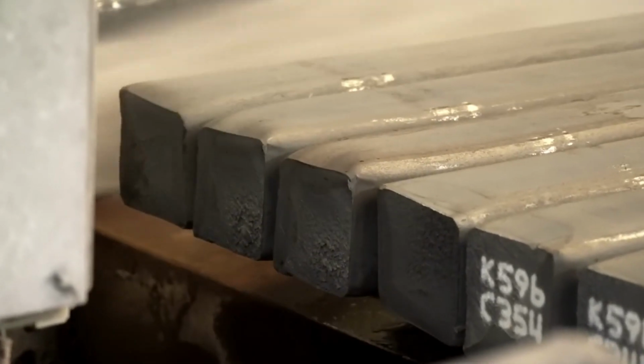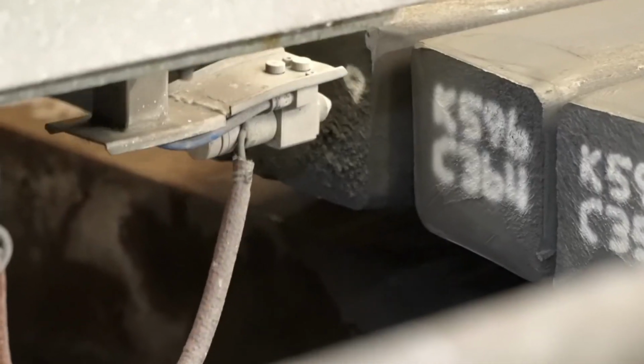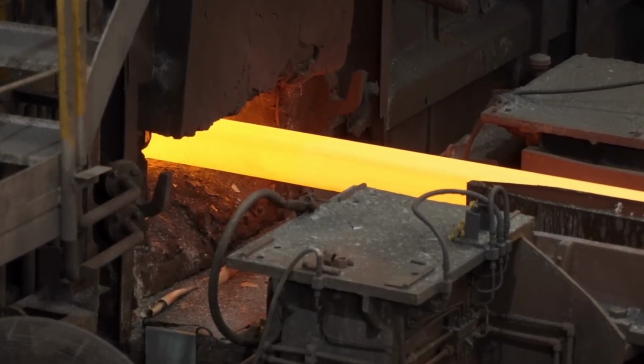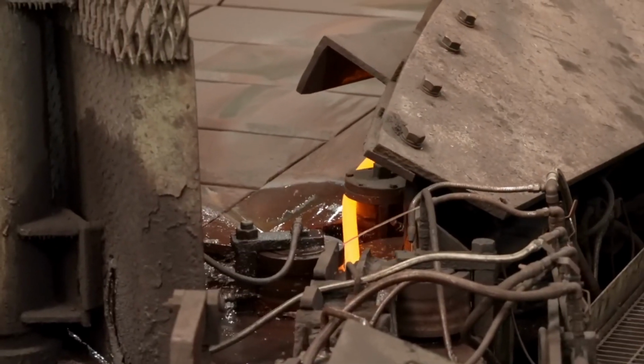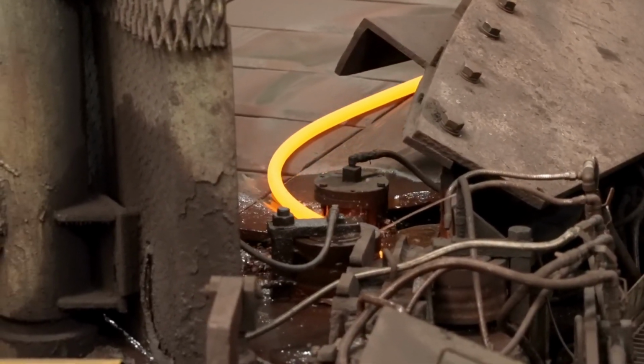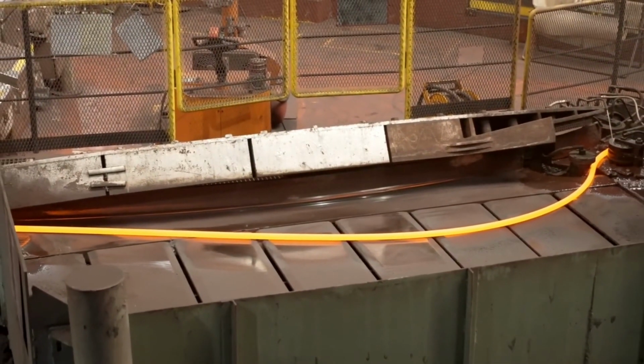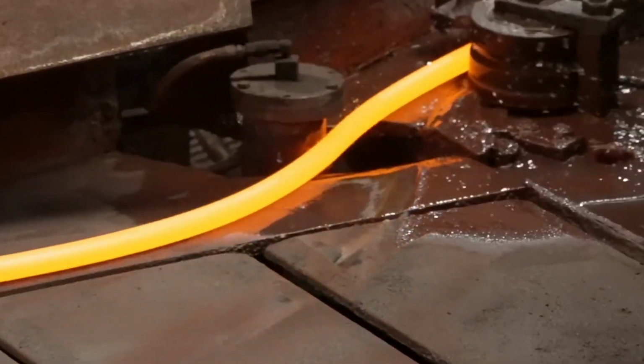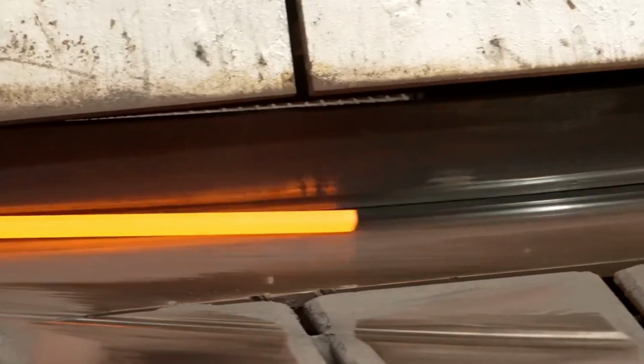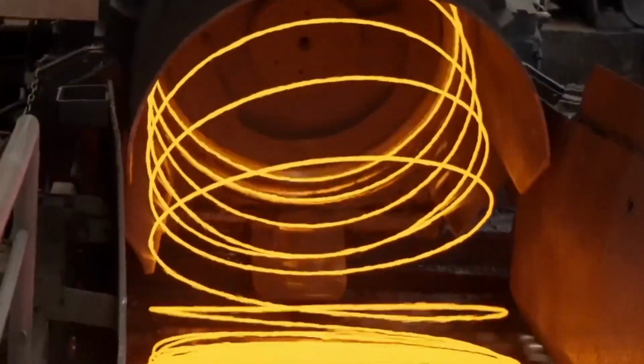Dozens of thermocouples monitor heat across the surface. If a cold spot appears, burners ramp automatically. If one region overheats, fuel drops instantly. Uneven heat creates soft spots and tears during rolling. Temperature uniformity enables controlled deformation. Now the slab is hot, but far too thick.